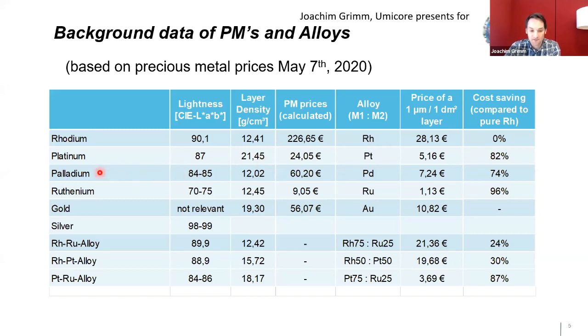If you compare with palladium or ruthenium, it's the same calculation. How much does 1 micron at 1 square dm cost? And here, just as a comparison again, the rhodium is our status. This is where all our calculation starts. We want to compare it with the rhodium. Platinum is 82% cheaper than rhodium in the layer of 1 micron on 1 square dm. It's 74% for the palladium, 96% for the ruthenium.